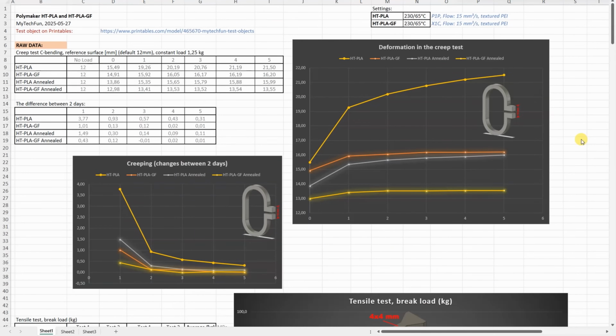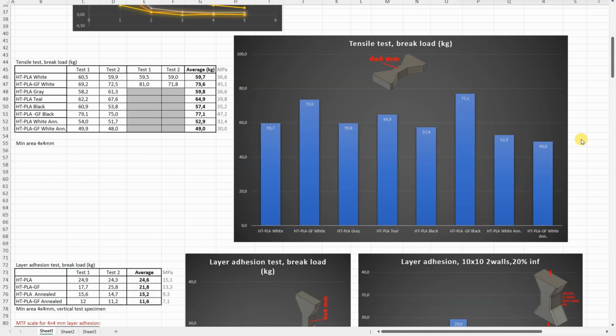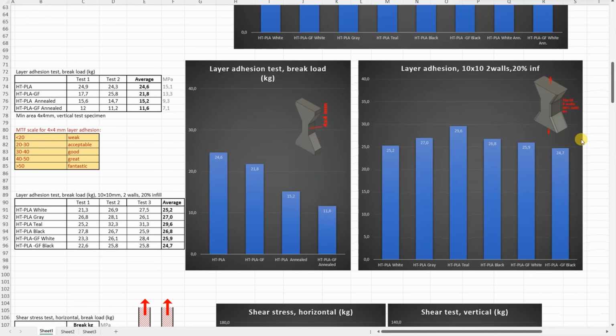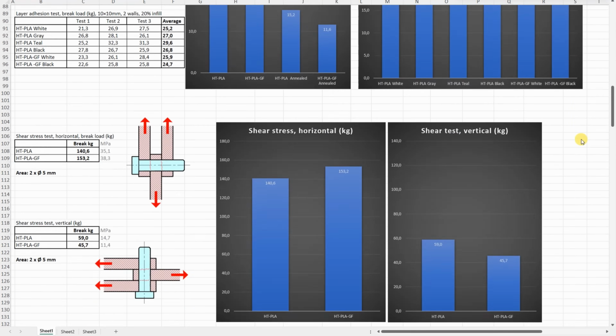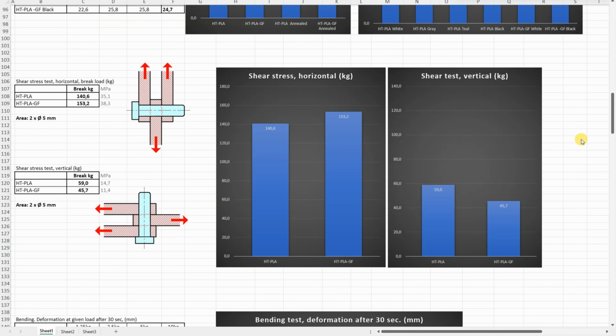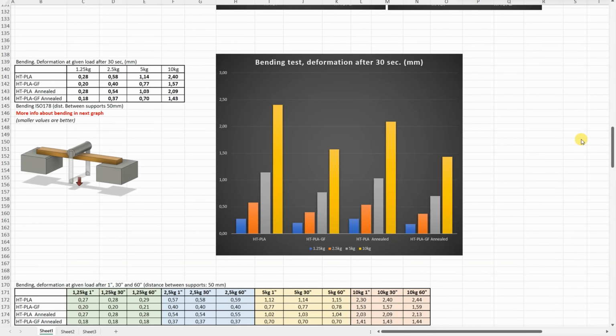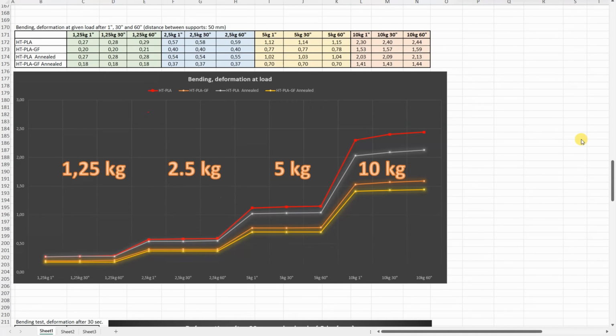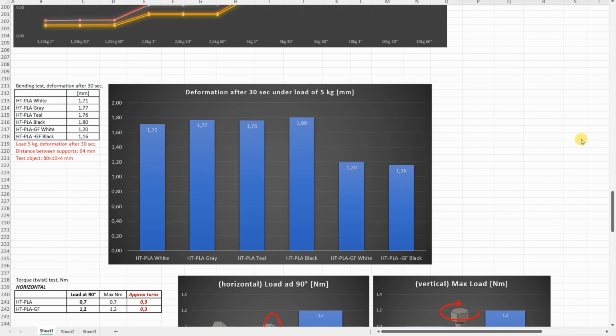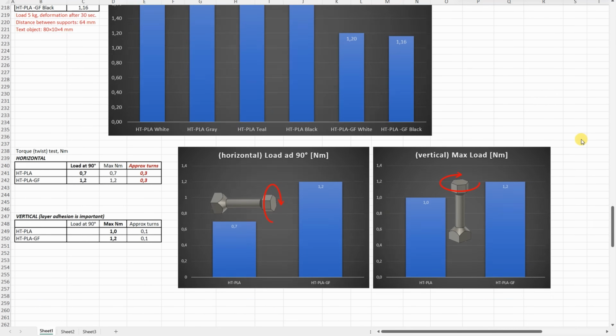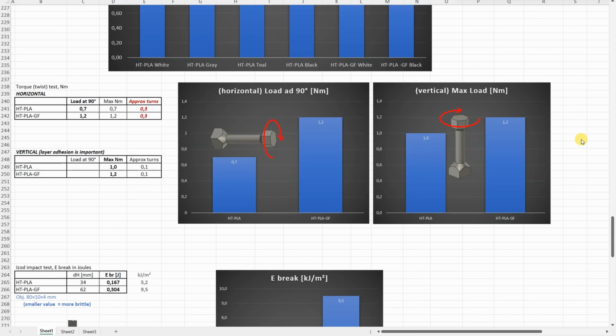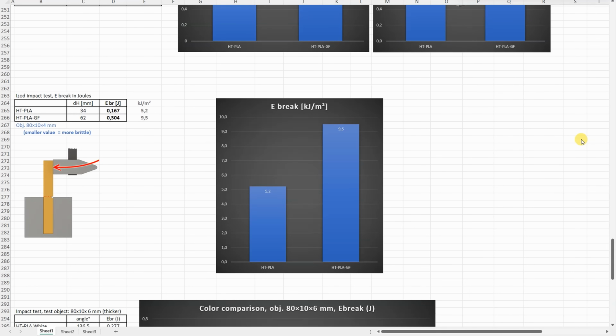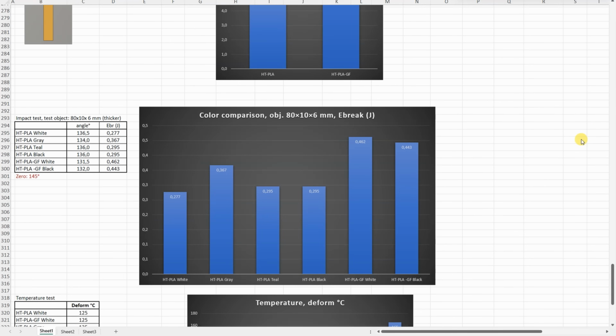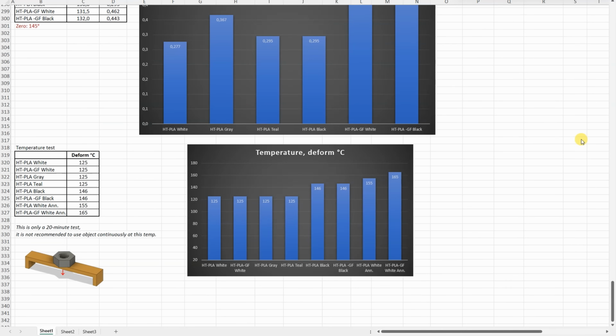All results one more time without any additional comments. Tensile test results, layer adhesion 2 types, shear test horizontally and vertically printed objects, bending deformations after 30 seconds, and this is more important, deformations after 1, 30 and 60 seconds. Bending test for the color comparison, torque or twist test, impact test, and this is impact test for the color comparison with thicker objects, and the temperature test.